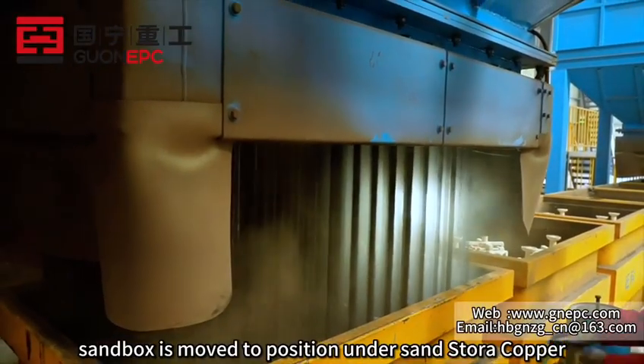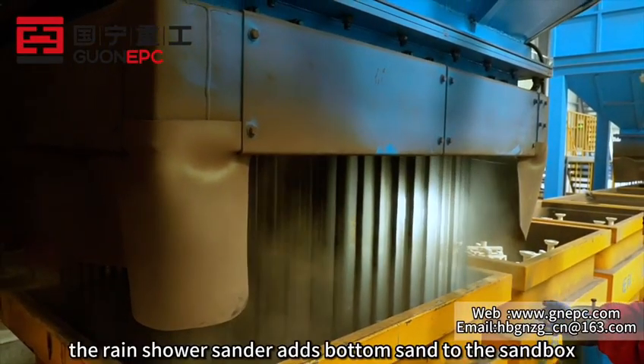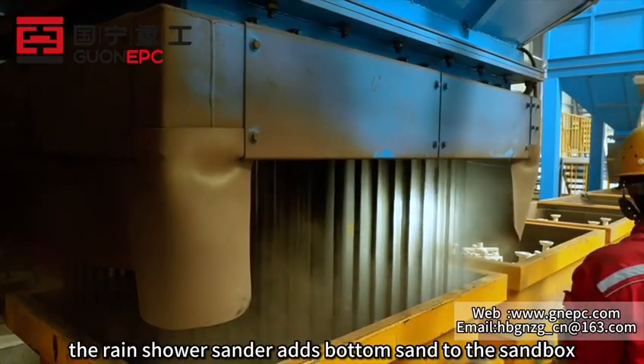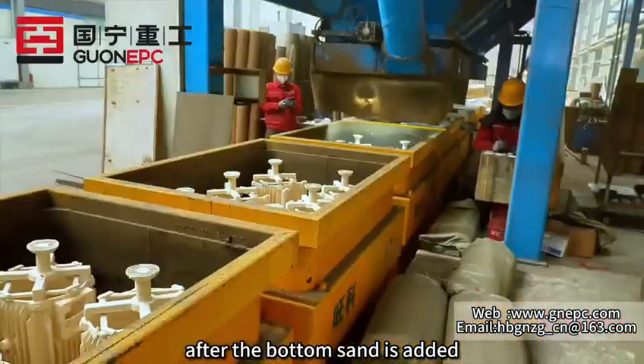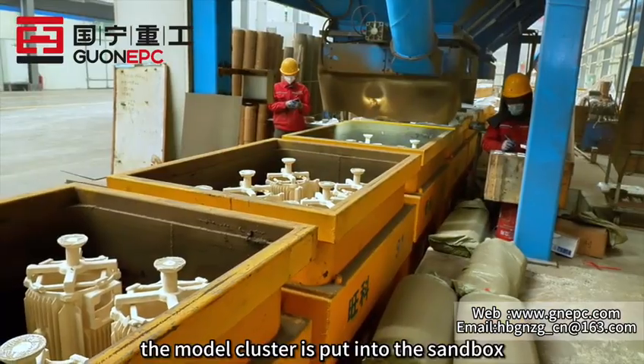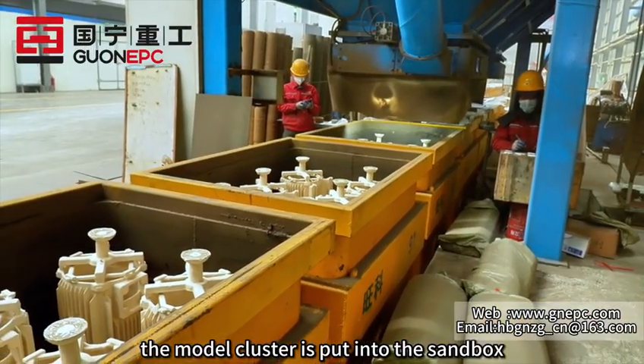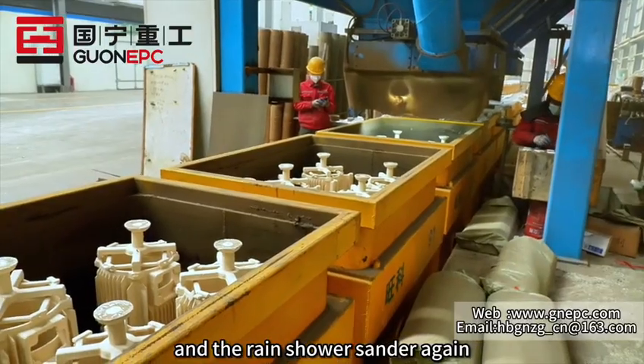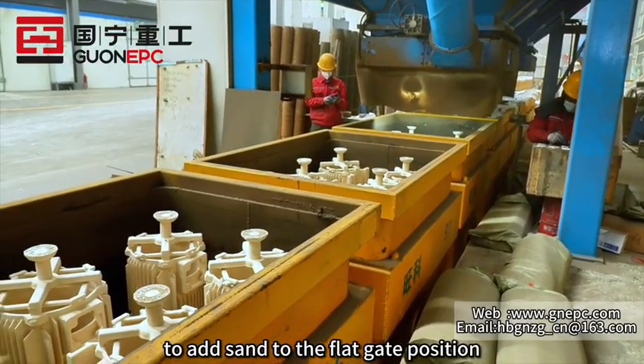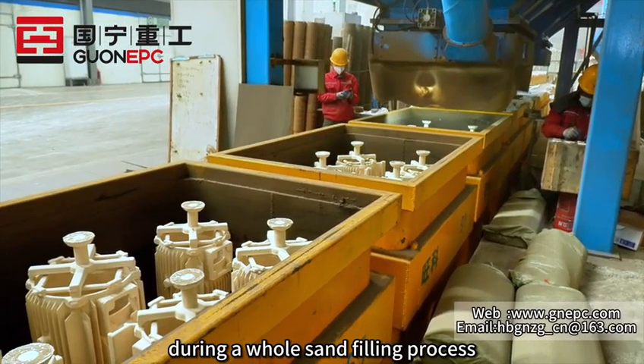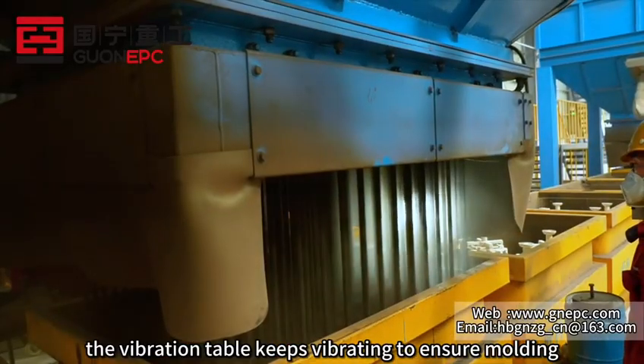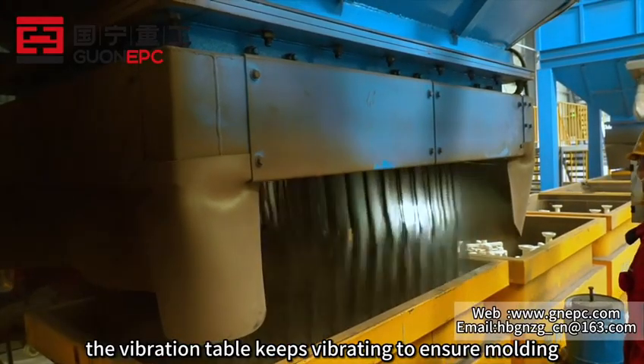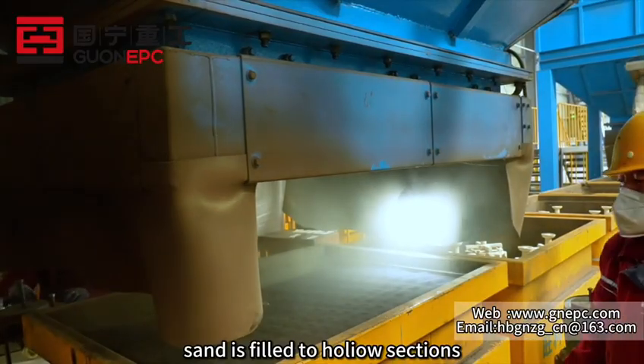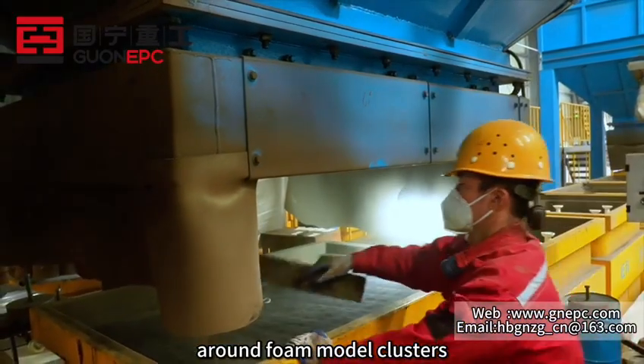The sandbox is moved to position under the sand storage hopper. The rain shower sander adds bottom sand to the sandbox. After the bottom sand is added, the model cluster is put into the sandbox, and the rain shower sander again adds sand to the flat gate position. During the whole sand filling process, the vibration table keeps vibrating to ensure molding. Sand is filled into the hollow sections around the foam model clusters.